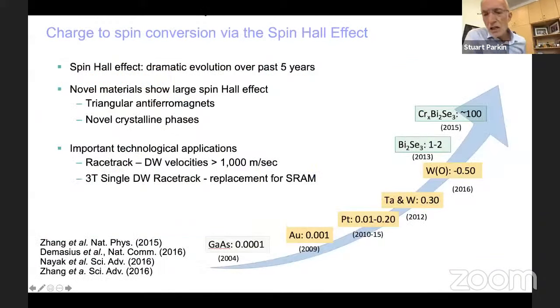And I wanted to point out here a very beautiful work by the Cornell group of Dan Ralph and Bob Buhrman, where they were the first to report significant effects, for example, in a certain special crystal form of tungsten, which is obtained in ultra-thin films, and in tantalum. When they first reported it, it was of the order of a few percent. Now it's of the order of 30%, and platinum, for example, is 20%. So these are huge numbers compared to what was believed and what was first shown in gallium arsenide. As I said, 15 years ago, it was 0.0001, and platinum and tungsten today are of the order of 20 or 30%. And now there are some other interesting materials.